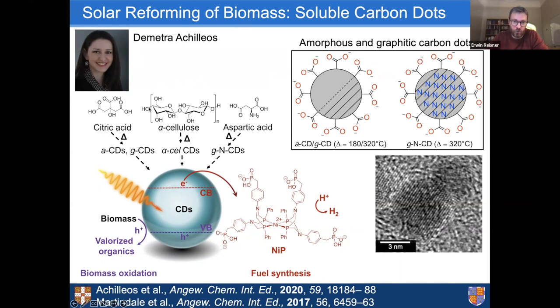You use this to make the carbon dots, and these cellulose-derived carbon dots can then photocatalytically degrade biomass or cellulose into organic acids, again with the co-generation of hydrogen from aqueous solution. And also here we are under benign pH conditions to drive this photochemistry.